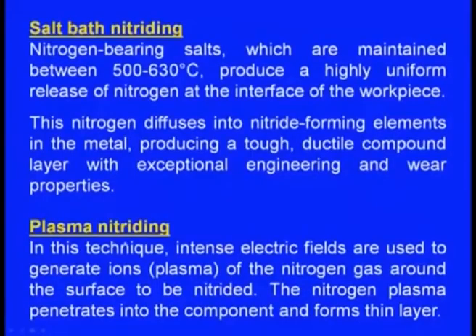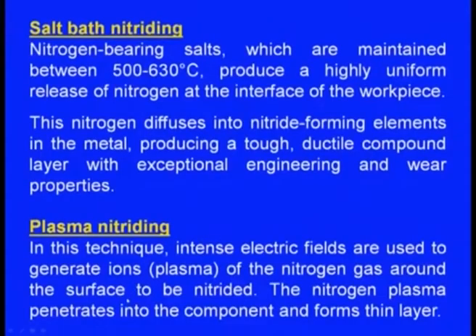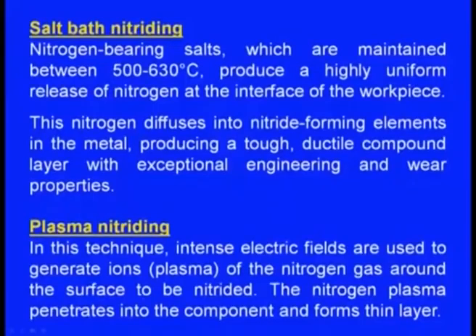Next one is plasma nitriding. In this technique, intense electric fields are used to generate ions or plasma of the nitrogen gas around the surface to be nitrided. Then the nitrogen plasma penetrates into the component and forms a thin layer which is very hard. So, that is plasma nitriding.